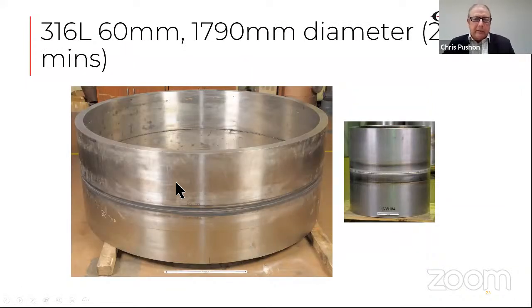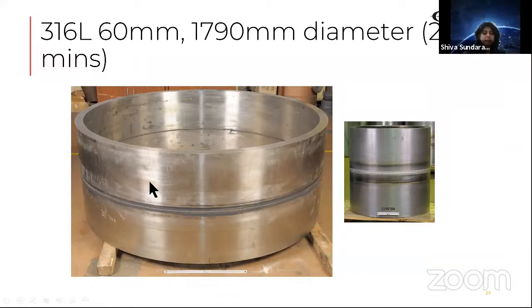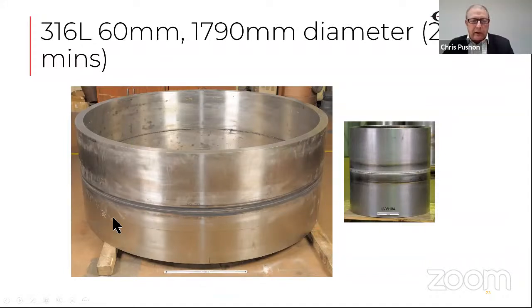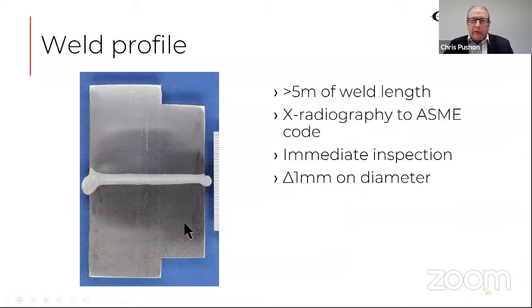So this is a demonstration. Again, we got a 316L austenitic stainless steel, 60 millimeter wall thickness tubular structure, and welded it using the local vacuum system. The big takeaway is it only takes 27 minutes from start to finish, but the big advantage is in terms of distortion. So we measured the shrinkage in length which was 0.5 millimeters, and we measured the shrinkage in diameter, which was less than 1 millimeter. So that gives you an impression of the distortion characteristics.